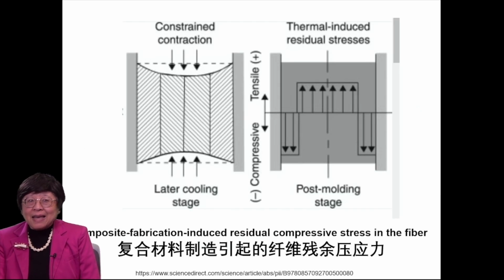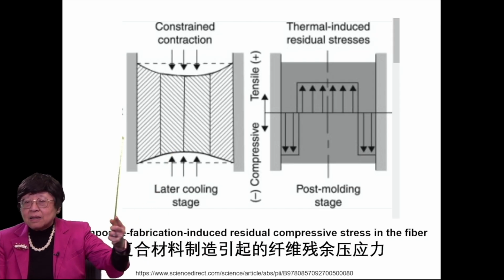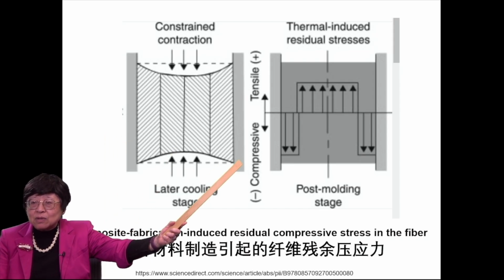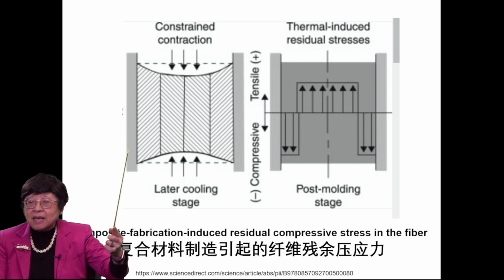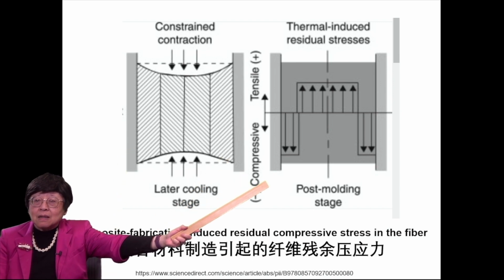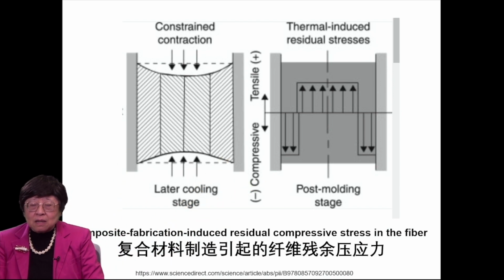Now, in making a carbon fiber polymer matrix composite, such as using epoxy resin as the matrix, then during the composite fabrication, the epoxy resin shrinks. As a result, it causes the carbon fibers to experience a compressive residual stress after the composite fabrication.